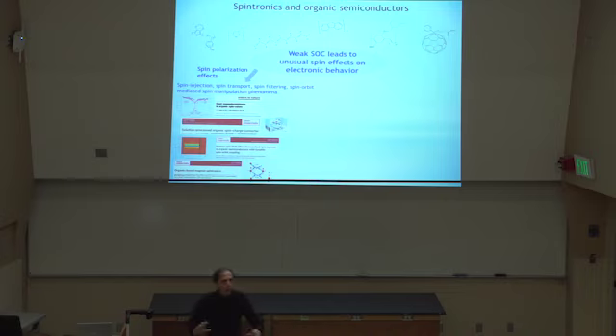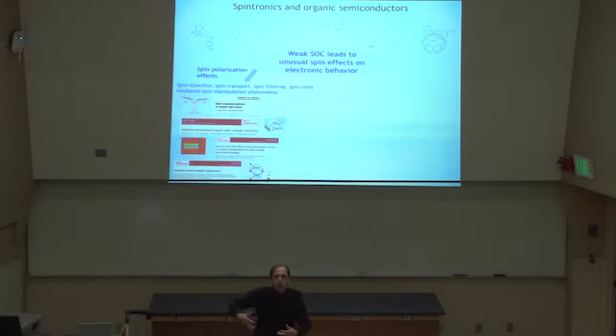That's usually what physicists refer to as spintronics. Essentially utilizing effects that are all about the injection of polarization, the detection of polarization, and then the propagation of polarization, meaning spin transport, and then spin-orbit mediated spin manipulation schemes that people have been thinking about in terms of spin transistors. And yes, people do study these topics and these mechanisms in organic semiconductors and other carbon-based semiconductors because weak spin-orbit coupling can imply in certain systems that you have very long spin relaxation times, spin lifetimes, and that translates then into very long spin diffusion lengths.